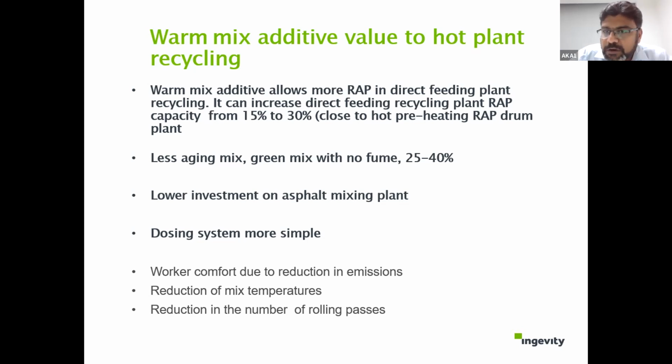It has already lost all its volatile material. Now when we want to reheat it, it is not going to behave the same way at the old temperatures, that same 160, 150. So I need to increase my temperatures much further if I want the same kind of response from this material. But that's not possible. Going beyond 180, 190 is just ruled out because there are a lot of other implications. So if you can get those properties within these temperatures, that is well and good.